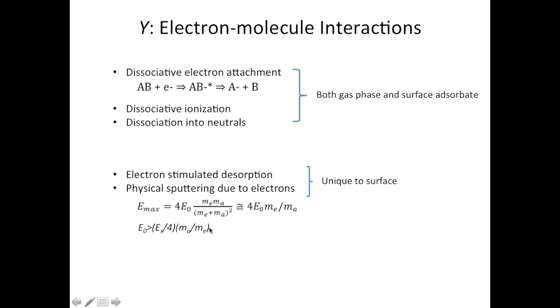Another type of reactions are unique to the surface. One of them is electron-stimulated desorption. It's similar to the dissociative reactions described above, but the end products are volatile, so they just escape from the surface without contributing to the film deposition.